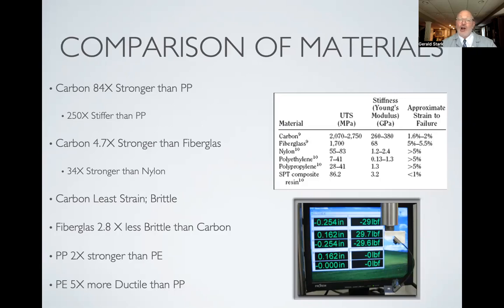So when we compare different materials, you can see when we use composites, they're very impressive. Carbon is 84 times stronger than polypropylene, 250 times stiffer than polypropylene. Carbon is 4.7 times stronger than fiberglass and 34 times stronger than nylon. But carbon's not a perfect material. Carbon is very brittle. In fact, carbon by itself is not particularly ductile. So carbon has the least amount of strain. So you need to bind that strength of carbon with the resin matrix. So fiberglass is about 2.8 times less brittle than carbon. So this increases the toughness and flexibility. Toughness is the ability to bend but not break, just like a good football defense.